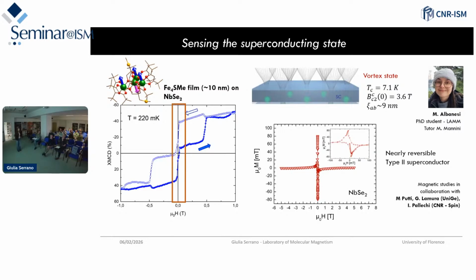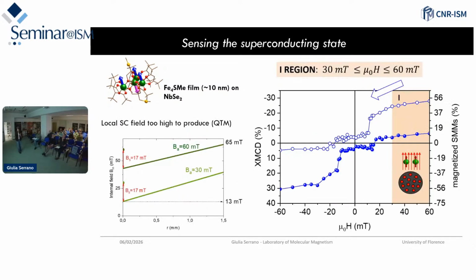So now I'm going to zoom into the most interesting region for us, in which we have this strange behavior of the hysteresis loop that we measure with the same method that I mentioned before on the Fe4 film. So what we have here is that when we scan the field from high field to lower field, we have more or less a constant trend of the magnetization that is similar to what we expect without the superconductor.